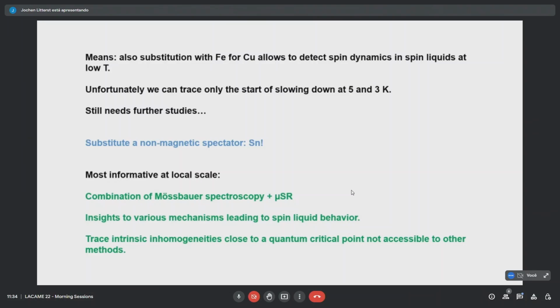Where I think is the special strength is that we can trace intrinsic inhomogeneities, which are close to a quantum critical point. That is the case, for instance, in the iron scandium sulfide, and also now in the latter case with the strontium copper double perovskite, where it's also suspected there is a quantum critical point just between the two different opposing magnetic orders, where they are most competing, and therefore, in this way, the local correlations are not dominated by the local exchange alone.